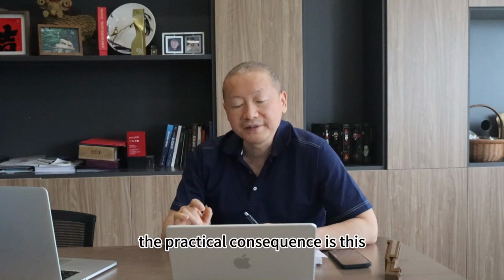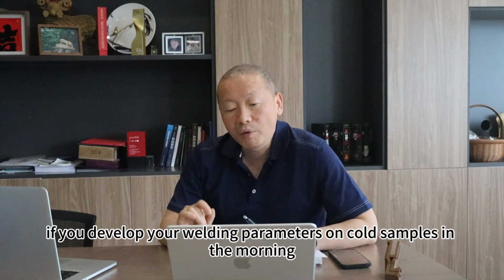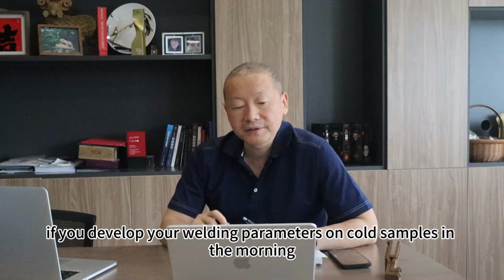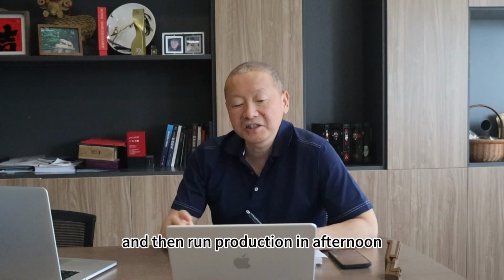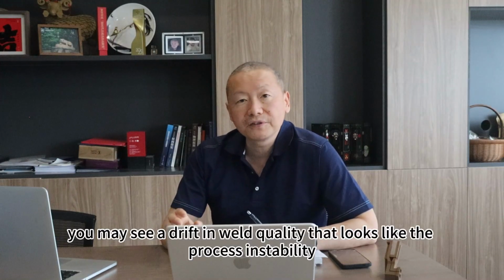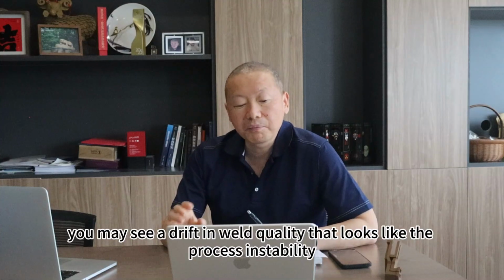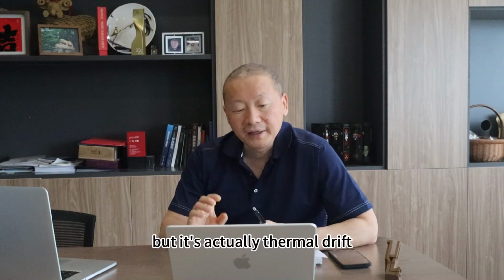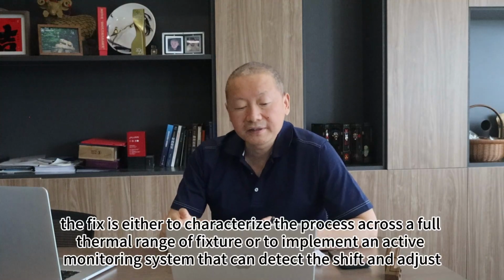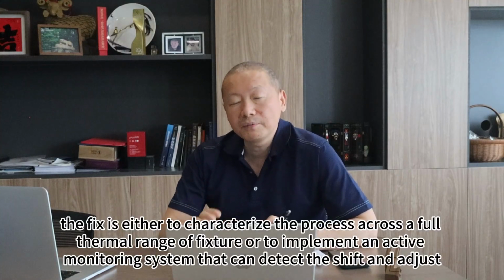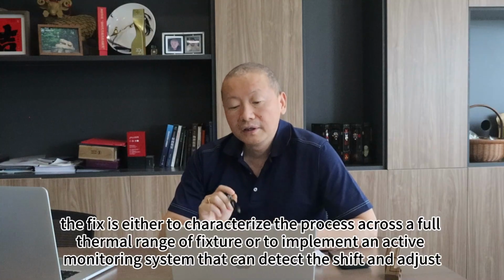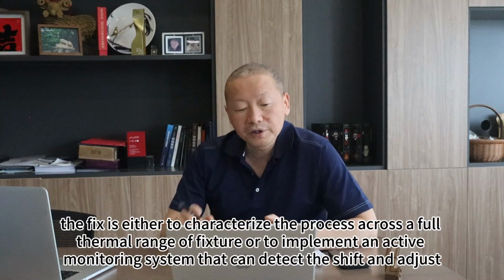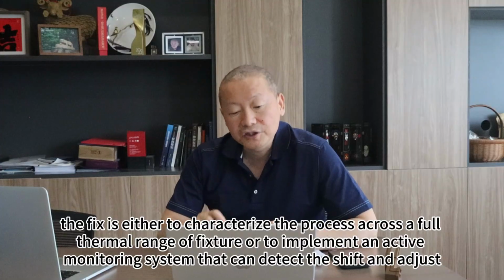The practical consequence is this. If you develop your welding parameters on cold samples in the morning and then run production in the afternoon, you may see a drift in weld quality that looks like process instability, but is actually thermal drift. The fix is either to characterize the process across the full thermal range of the fixture, or to implement an active monitoring system that can detect the shift and adjust.